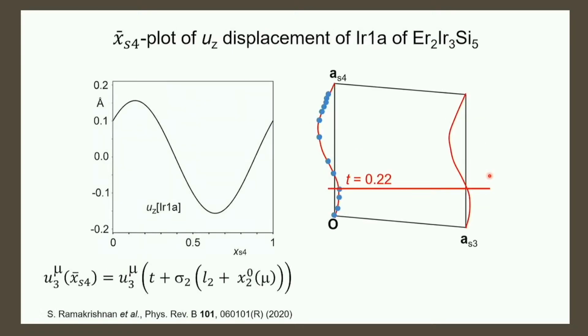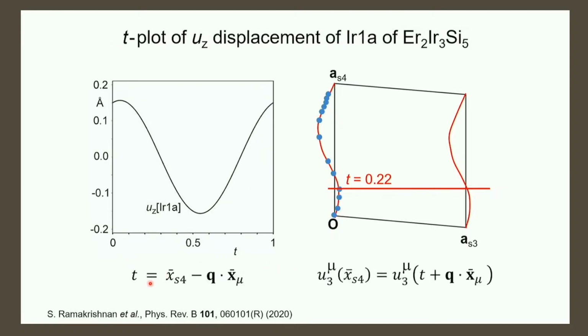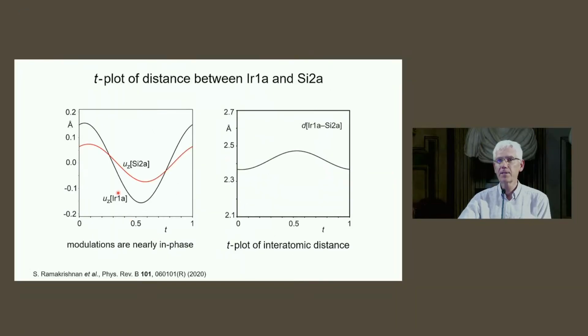And we can do that for this iridium atom I've shown to you before. This is the position of the iridium atom. And we can do that as a function of the argument, x4, but that's not what we want. We do it as a function of t. And you can see it just shifts along the horizontal axis because we subtract a certain amount from the x4. But this certain amount depends on the atom we have, so we subtract different amounts q dot x for different atoms. And that's exactly what we need with a function of t. We get everything in the same physical space. This is a close-by silicon atom, and you see they modulate nearly in phase in such a way that the distance doesn't vary too much. And that's what you can learn, for example, from such a T-plot.